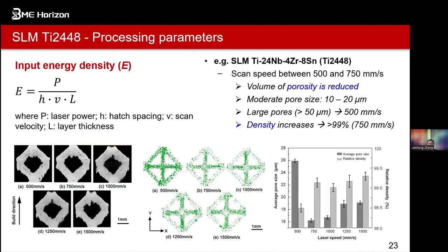So that's why from here, I put some conclusions of this part. The volume porosity is reduced by increasing the scan speed, and also the pore size is roughly from 10 to 20 micrometers, and we still produce large pores. That's because of the laser scan speed. So even this is still a way to optimize. That's why we still need the knowledge to process these things.